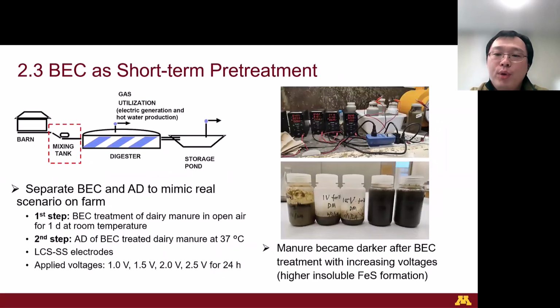To simulate the real farm conditions, we further separated our BEC treatment from anaerobic digestion of dairy manure and tested the short-term BEC treatment, or pre-treatment, before anaerobic digestion. We applied an external voltage for 24 hours to the manure first, then subjected it to anaerobic digestion without the BEC system. With the increasing voltage, we can see that the manure became darker and darker with the formation of more black insoluble ferrous sulfide precipitates.